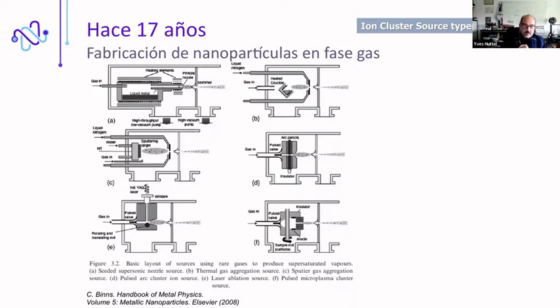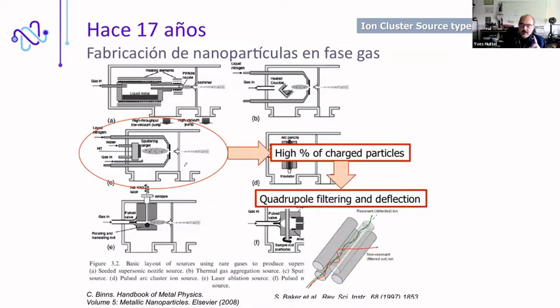In all cases, you create a vapor of atoms using a crucible, an oven, a laser, or a magnetron. With the years, the systems that work with magnetrons became more popular because they are easier to manipulate and use. The other advantage is that the nanoparticles or clusters that you produce are highly charged. Approximately 80% of them are charged, which means that you can filter them if you want to reduce the size distribution.